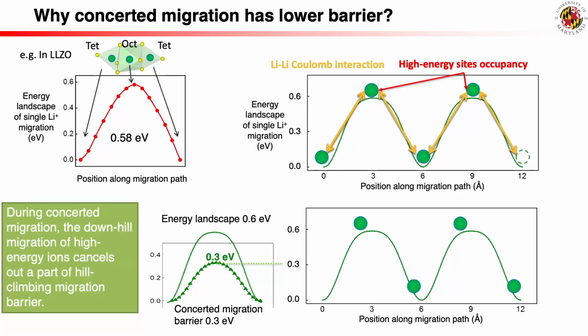And the paper also talks about the energy landscape at these high energy sites. Yeah, that's important too. What's so special about it? It needs to be relatively flat. Flat. Yeah, so that ions can easily escape and participate in concerted migration. So it's like a launching pad. Exactly. If the energy well was too deep, it would be harder for the ions to get out. And the simulations actually showed evidence for this flat energy landscape. They did, at the high energy sites. So it all ties together.